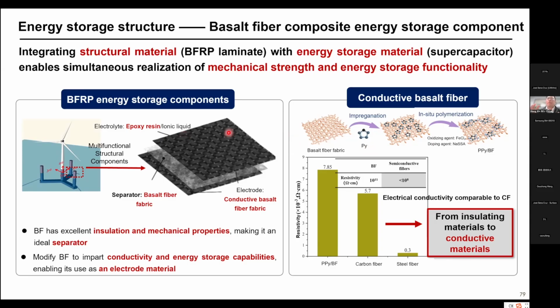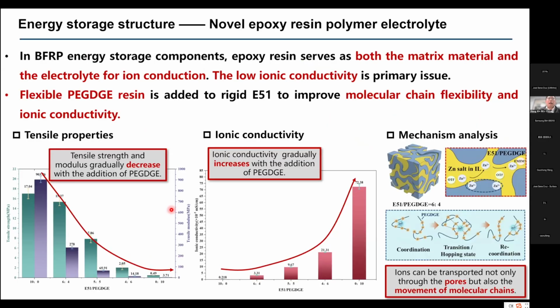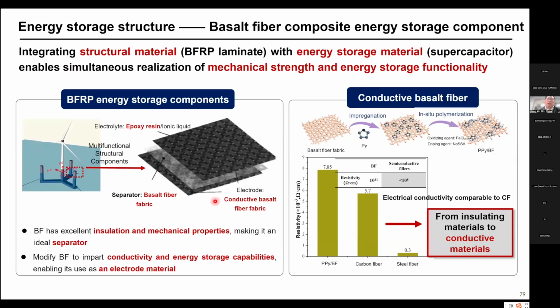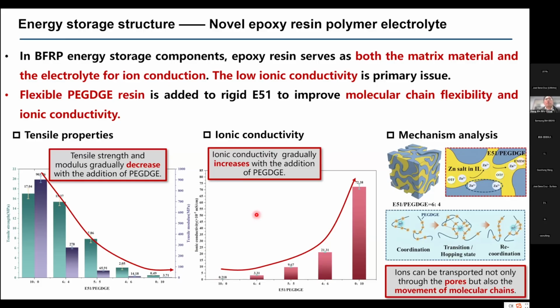So this one also has very good mechanical properties. At the same time, it has this energy storage ability. So after modification, basalt fiber can achieve, not as good as carbon fiber, but a similar function. And also, not only for the basalt fiber, we can also treat the epoxy resin with PEG. But PEG makes the epoxy resin very soft, but its ionic conductivity is greatly enhanced. So make it to be this kind of electrolyte material. So with the electrolyte material, with the isolation, and also with the electrode conductive basalt fiber, we can produce this kind of energy storage component.